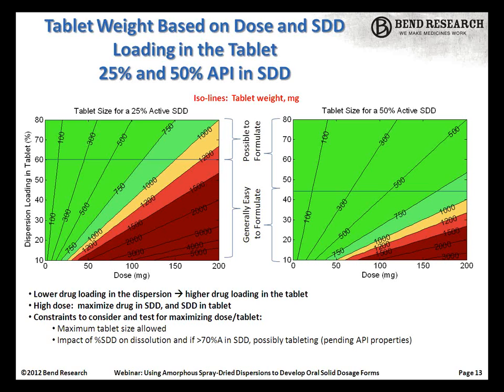So we're going to transition over a little bit from talking about the SDD technology in and of itself, and Chris mentioned how that starts marrying up with the tablet. In the case that he used here, this 100 to 200 milligram tablet dose is probably the most common. That has to do primarily with the fact that most of the amorphous solid dispersions that have the optimal physical stability, as well as performance in vivo or in vitro, I guess, initially, do fall into this 25 to 50% active range. So the tablet sizes here typically are in the 400 to 800 milligram size.